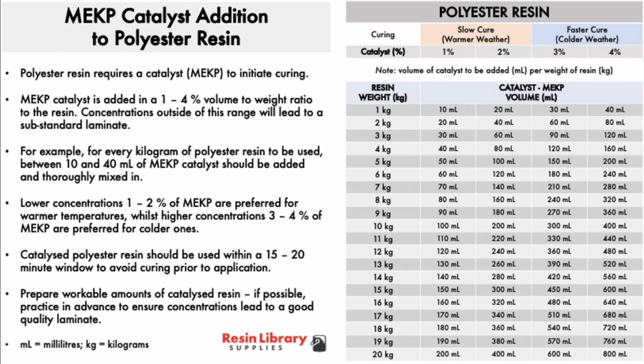Polyester resin requires a catalyst, typically MEKP, to initiate curing. MEKP catalyst should be added in a 1 to 4% volume to weight ratio to the polyester resin. Concentrations outside of this range will lead to a substandard laminate. So for example, for every 1 kilogram of polyester resin to be used, use between 10 and 40 milliliters of MEKP catalyst and thoroughly mix it in.